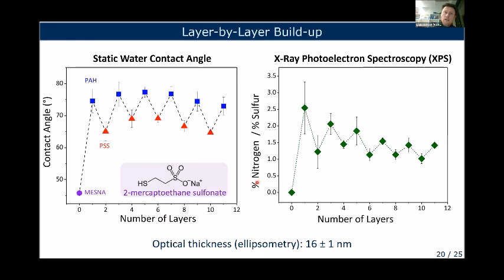So if you look at the percentage of nitrogen over sulfur, so one is taken from one polyelectrolyte and the sulfur is present only in the polyanion. So if you look at the ratio between the two, again, you see alternating plots from which you can learn that after every next dip, indeed, you change the overall surface again with the polymer that you used in the dipping.